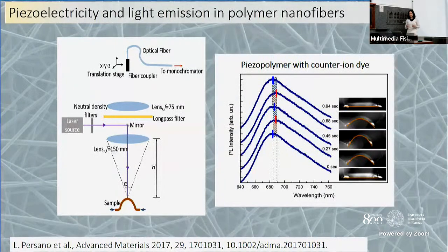And the final result is that if you measure the photoluminescence from the fibers, depending on the position of the fibers, which means depending on the amount of stress that you're applying to the fiber during bending, you can see that the main peak of the emission can be shifted in a reversible way. So it can be shifted a few nanometers according to the strain rate that is applied, as you can see here in the pictures.